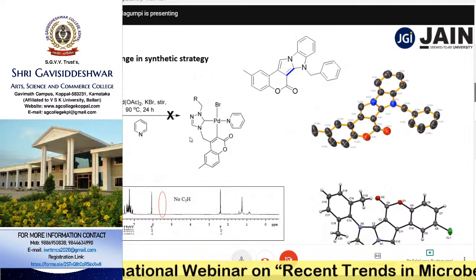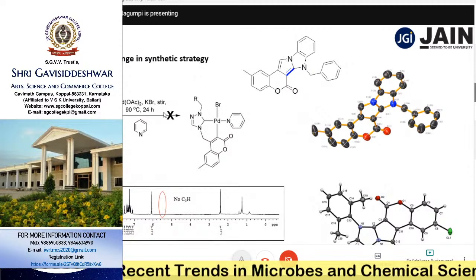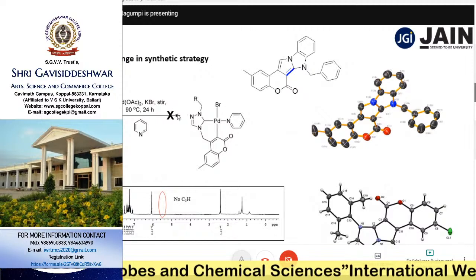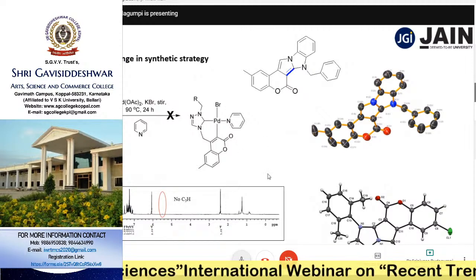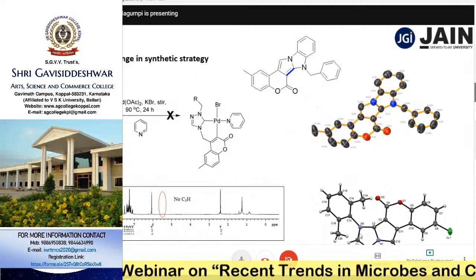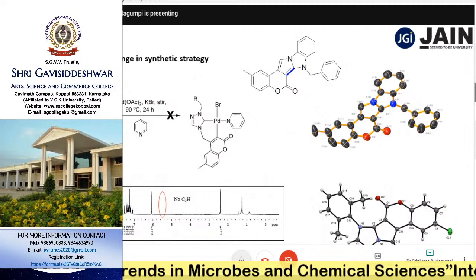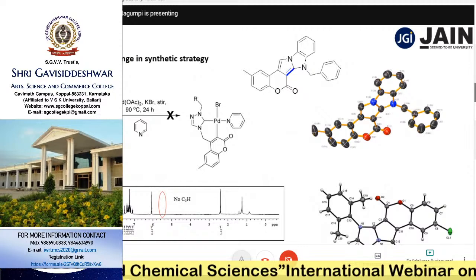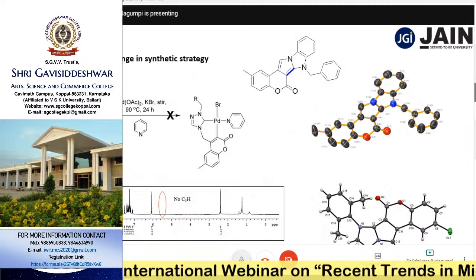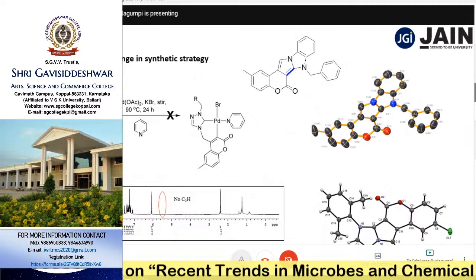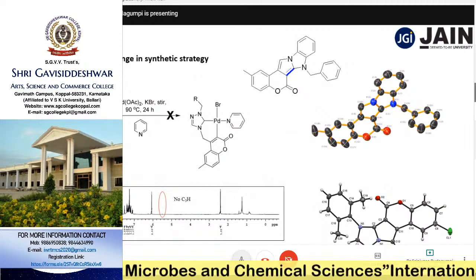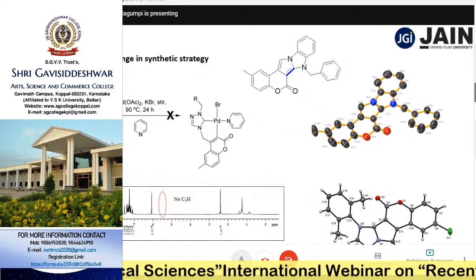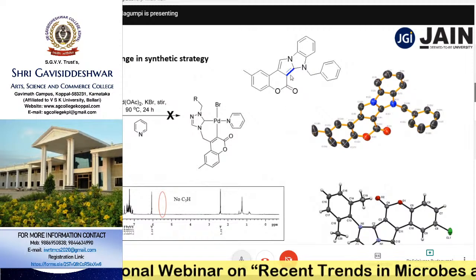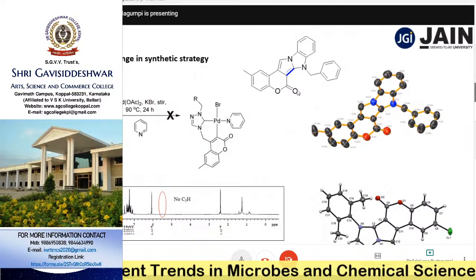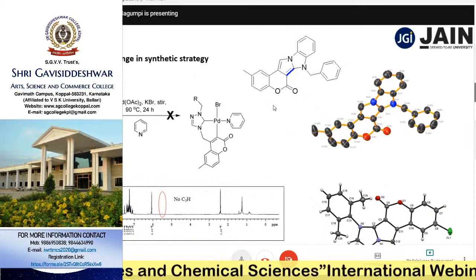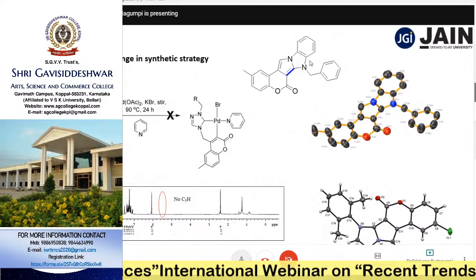So we thought that this particular complex is formed, but its X-ray analysis helped us to establish the exact structure, which says that this is not a complex. Instead, that has given some organic transformation. So this is an organic transformation considered as crossed dehydrogenative coupling. For example, this hydrogen and this hydrogen have been dehydrogenated, and the carbene-carbon, which is formed at the fifth carbon atom of triazole, and C3 of coumarin are coupled together. So that is a new bond formation here. This resulted in the formation of a fused triheterocyclic system, which is having coumarin, pyrrole, and azole systems as well.